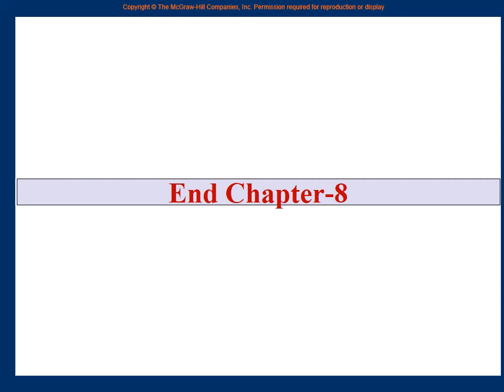Then today we started the eutectic, binary eutectic. It is still binary, so there are two materials, for example, lead and tin. But there is one special point. Normally, there are two solids, alpha and beta, so it is non-isomorphous. But on one side, when you start to cool, the liquid becomes alpha plus liquid, and then it becomes alpha plus beta. On the other right hand side of the diagram, the liquid, when you cool it, becomes beta and liquid, and then it becomes alpha plus beta. But there is one point which is the eutectic point, where the liquid suddenly becomes alpha plus beta, two solids. That is called the eutectic reaction.